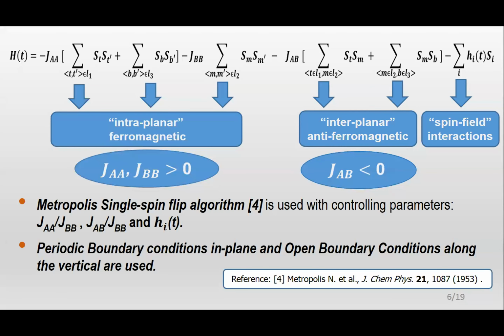As I said just now, intraplanar ferromagnetic terms have the coupling constants JAA and JBB greater than 0, that is positive, whereas the interplanar antiferromagnetic terms have their coupling constant JAB negative, and the sixth term, which has H_i in it, is basically the external magnetic field at site i at time instant small t. In the simulation, we have used Metropolis single spin flip algorithm with the controlling parameters being the ferromagnetic ratio, that is JAA by JBB, antiferromagnetic ratio, that is JAB by JBB, and the local field H_i, which is basically drawn from a uniform random probability distribution. The mid-layer coupling strength, that is JBB, is basically the dominant one and is taken to be equal to unity in this case.